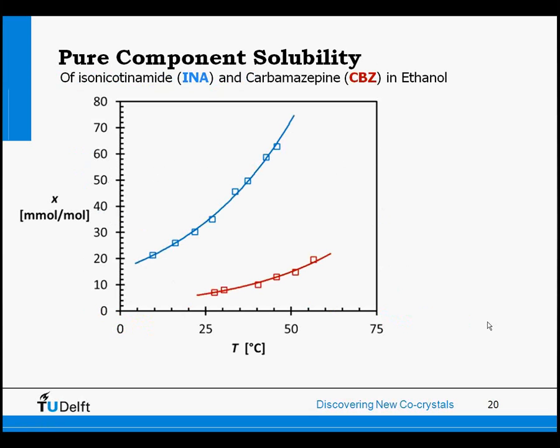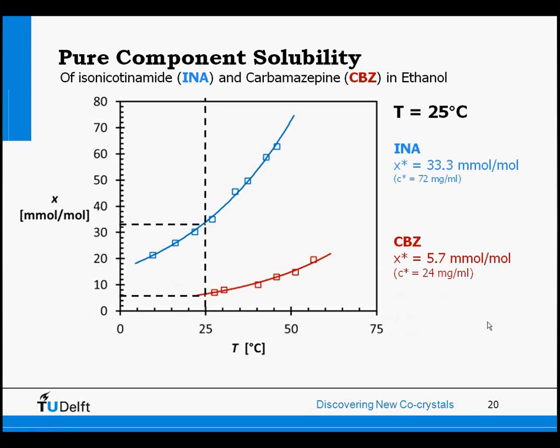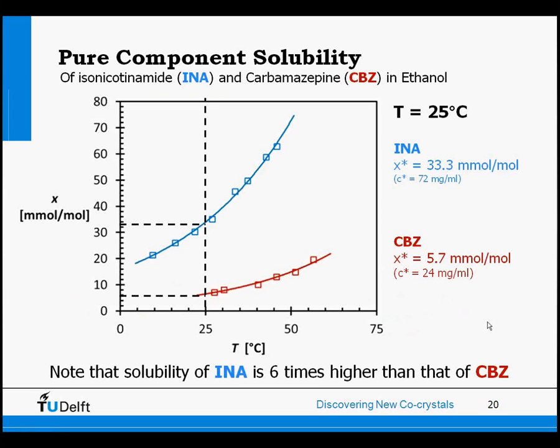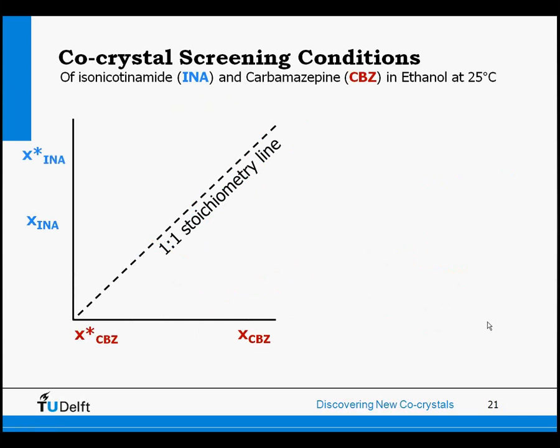So here again is the mole fraction against the temperature in degrees Celsius. The blue line is isonicotinamide, and the red line is the solubility line of carbamazepine. You directly see that the solubilities are quite different. The isonicotinamide solubility is at least 6 times higher than the carbamazepine solubility. We can determine now the solubility at 25 degrees Celsius. For isonicotinamide, that is 33.3 millimoles per mole, and for carbamazepine, it's 5.7 millimoles per mole. So it's 6 times higher solubility for isonicotinamide. And we will have to account for that in our discovery of the new co-crystals for isonicotinamide and carbamazepine.